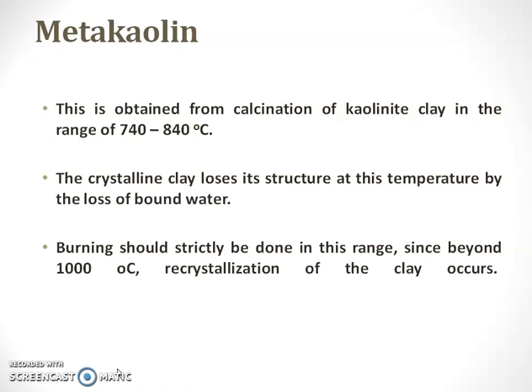Highly reactive metakaolin is obtained from the calcination of kaolinite clay in the range of 740 to 840 degrees Celsius. The crystalline clay loses its structure at temperature by the loss of bound water. Burning should be strictly done within this range — it should not go beyond 1000 degrees Celsius, as recrystallization may occur.